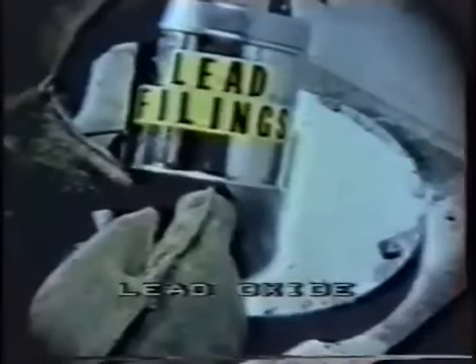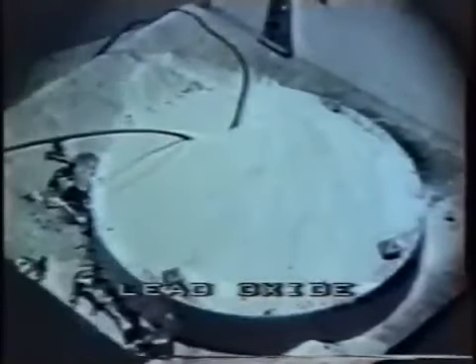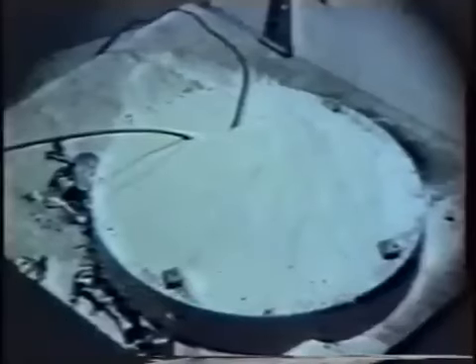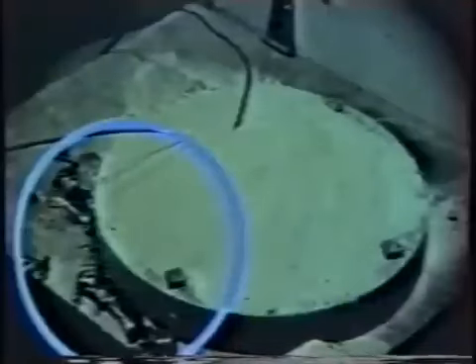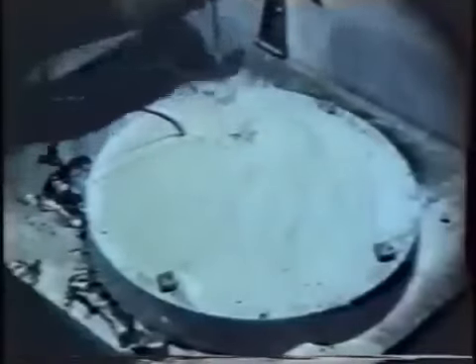Another way of extinguishing a fire, which has been used in several of the labs, is to use graphite powder. Graphite, again, being a good smothering agent, hopefully removing heat. One of the tests that was rather spectacular was the use of lead. We thought maybe the lead would absorb some heat by melting. Well, it melted all right, but it formed an alloy with the plutonium metal and spewed out a low melting alloy.